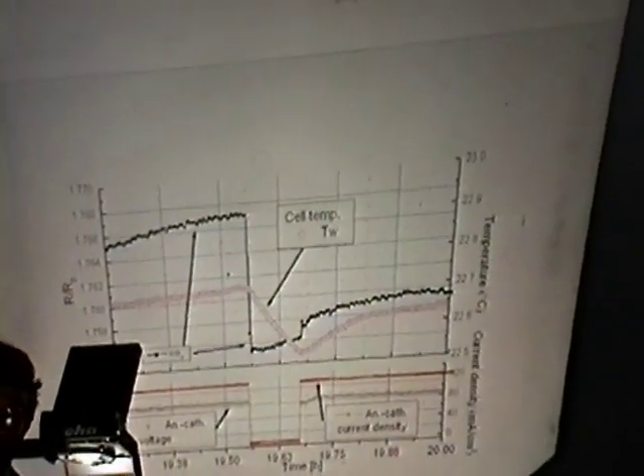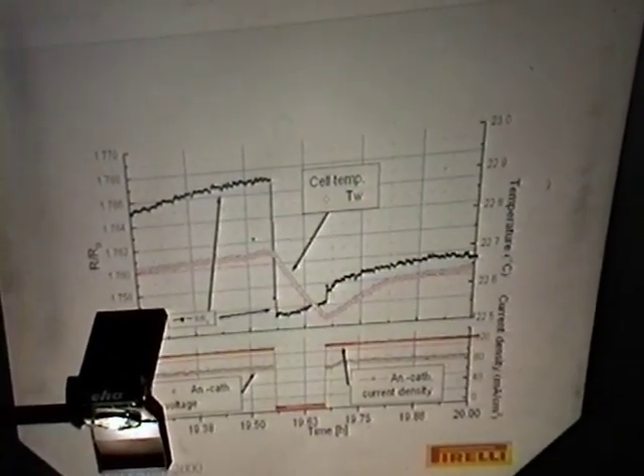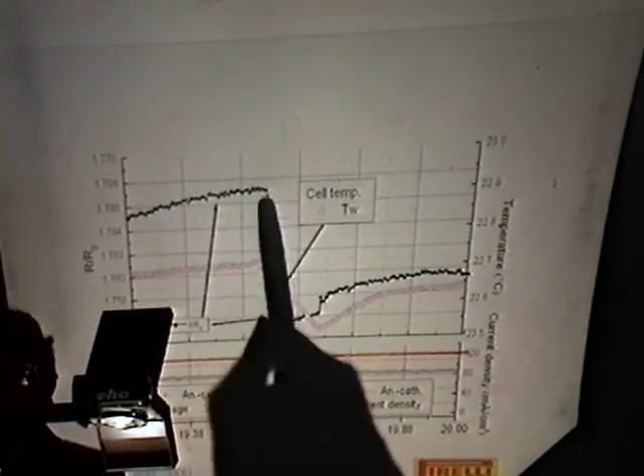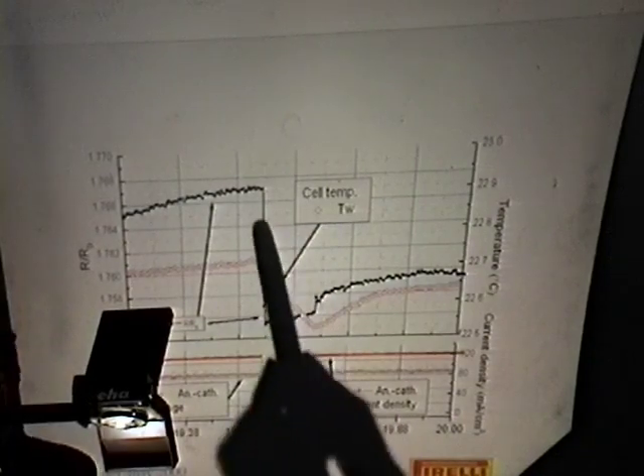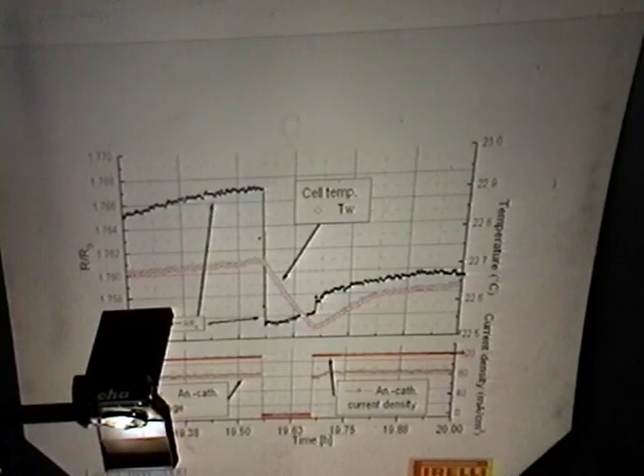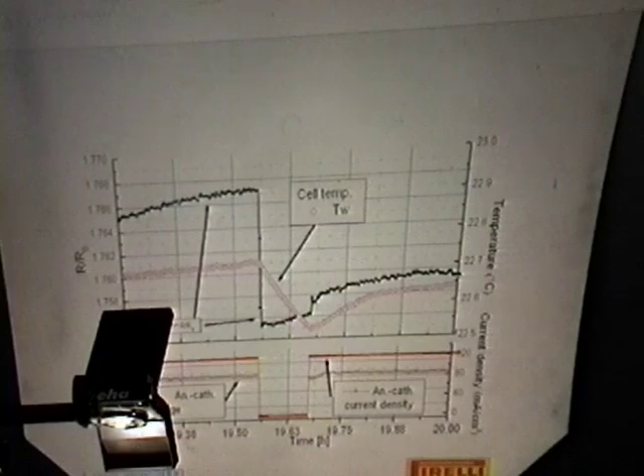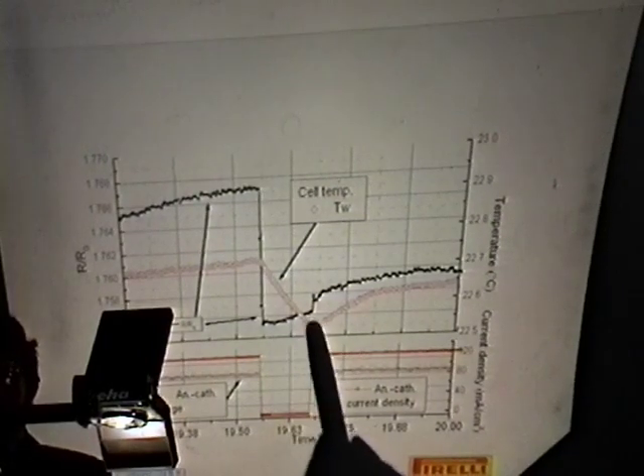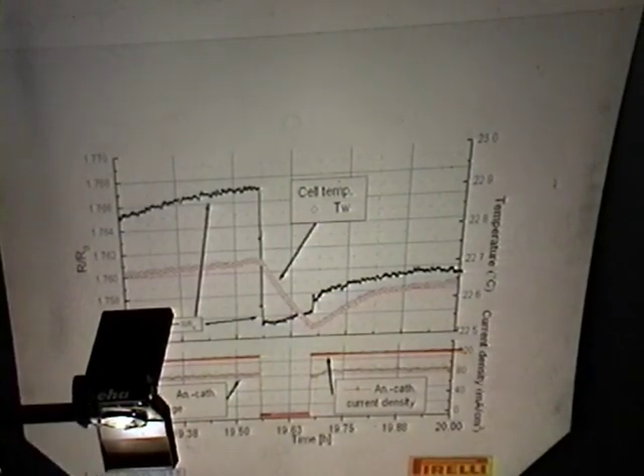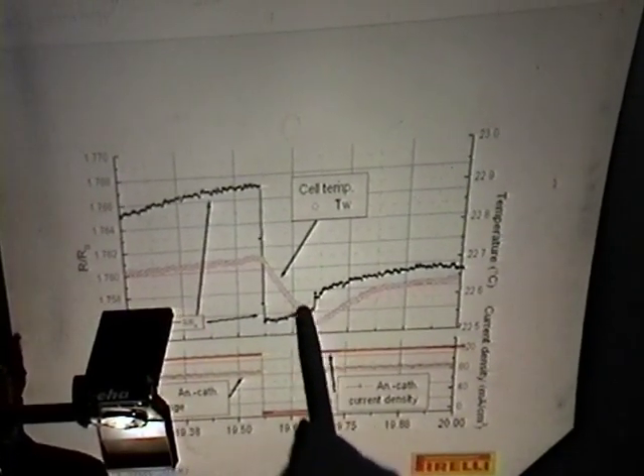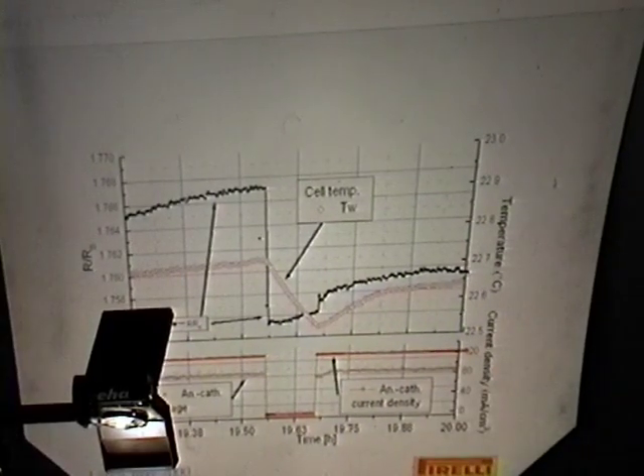Yesterday Celani saw similar results. We have a medium loaded wire, 1.76. At this point we switch off the current. We see a sudden decrease of the resistance in about 30 seconds. A possible explanation is that the wire was at a higher temperature when the current was on. And then the wire slowly deloads, only slowly because in this case we used a lot of mercury that blocks deuterium in the palladium. When we switch on the current again, we see a little increase of the resistance, but we did not come back to the previous value. Unfortunately, we saw this effect only once.